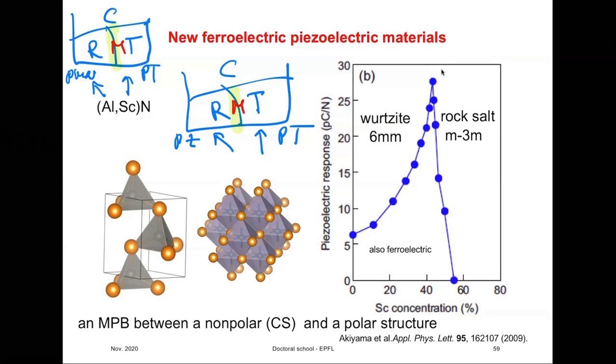Here it's different. Here we have a polarization in this direction and 0 here. So it's not a question of polarization rotation. Here we are talking about polarization extension and contraction. So it goes from 0 and then it softens for contraction of polarization. It could have some, of course, rotational character, but with respect to this boundary, it's from 0 to some other value.